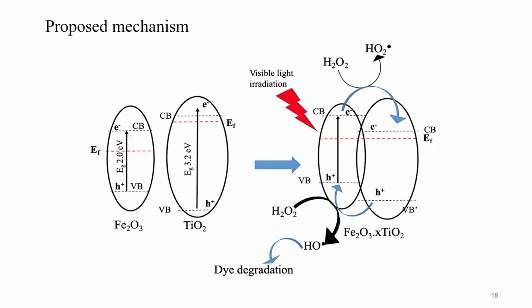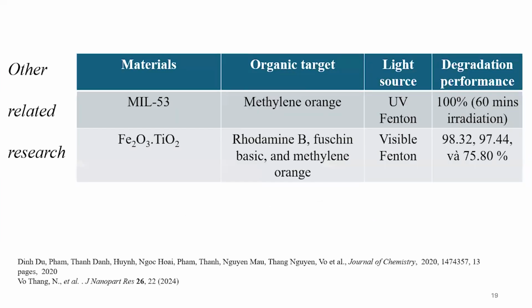And of course, for the mechanism, we believe that there is a rearrangement of the electronic structure within the material, suppressing the recombination of photo-generated electrons and holes in the material, and that will improve its photocatalytic behavior. We also do other MOF-based materials for this kind of application. For example, we did MIL-53 for the degradation of methyl orange.